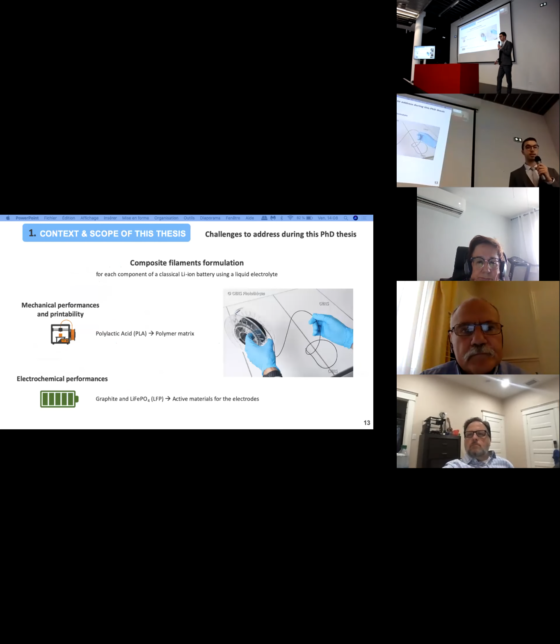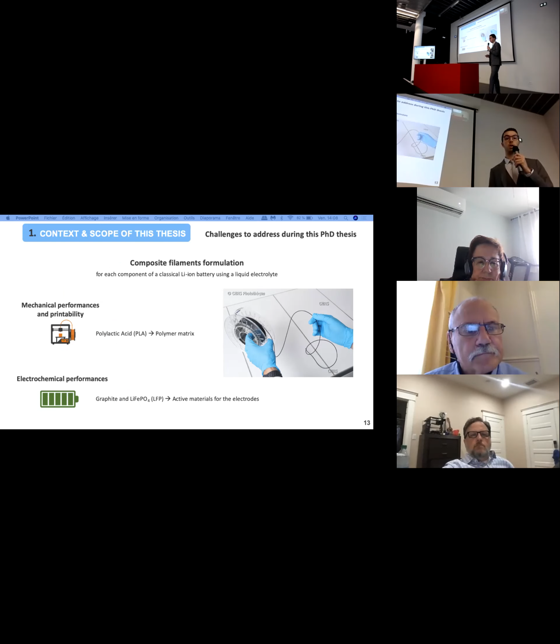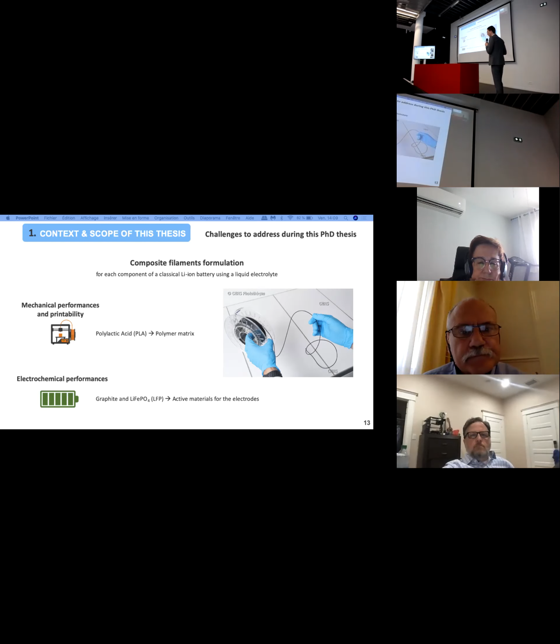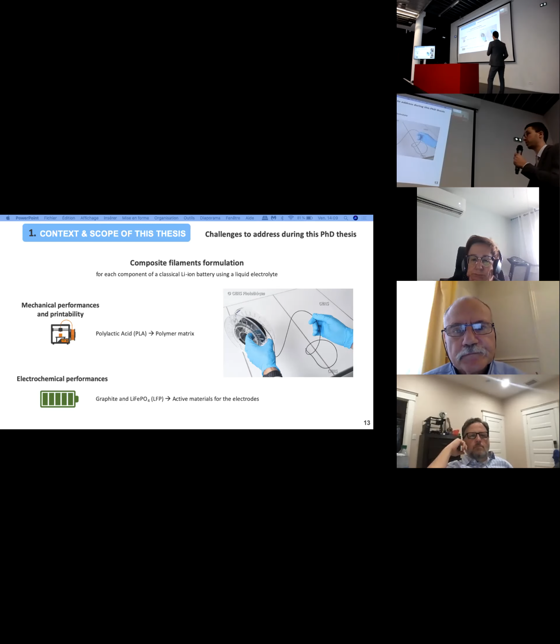So here are the challenges that we needed to address during this PhD thesis. The first part of this PhD thesis was focused mainly on the composite filament formulation, corresponding to each component of a classical lithium-ion battery using liquid electrolytes. In order to confer some mechanical strength to the filaments, we decided to use polylactic acid, PLA, as the polymer matrix. Why PLA? Because first of all, this is a green polymer made from corn. And also PLA is the most used polymer for FDM applications. Concerning the electrochemical performances, we decided to choose classical active materials such as graphite and lithium iron phosphate for the negative and the positive electrodes, respectively.